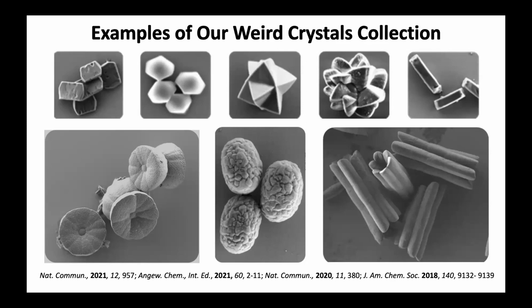You can see here a 3D Star of David and kind of undefined but beautiful structures shown here. We have Chiara's flowers. These actually have a hidden chirality built into the morphology, that you can see by micro-CT measurements. We have the dinosaur eggs of Vivek. You see here crystals that have a kind of multi-domain appearance. And we have another structure that is hollow, and you actually have 6 rods connected with each other. So these are all single crystals, although they don't appear like that. The uniformity of these systems is also very high, quite unique.